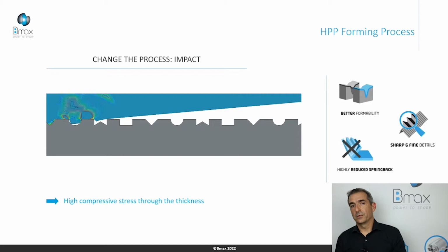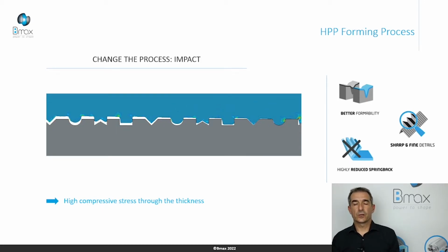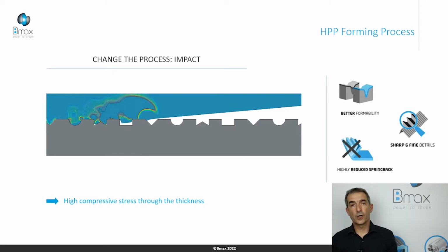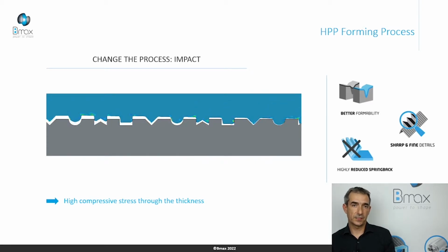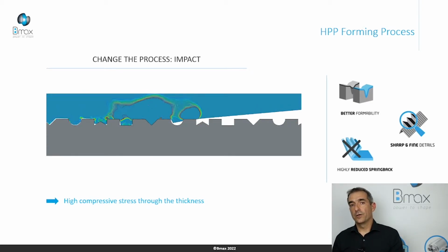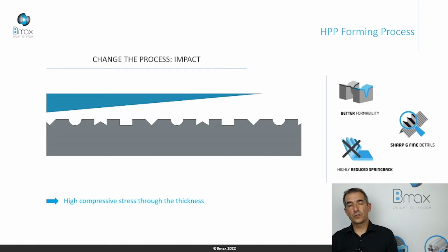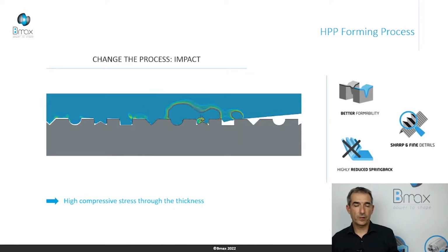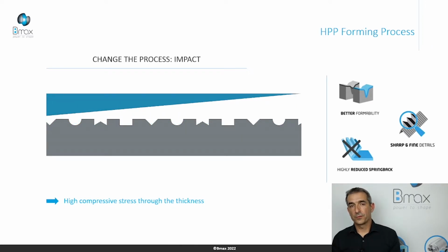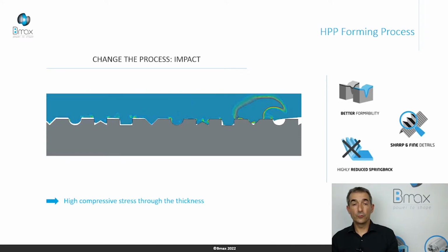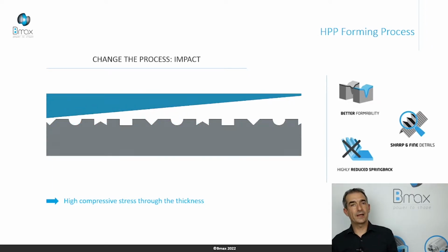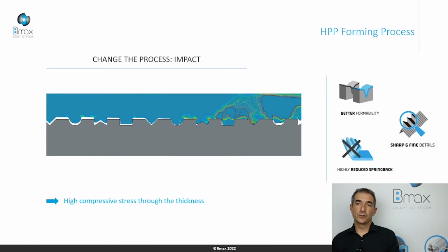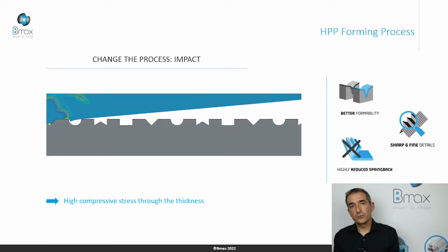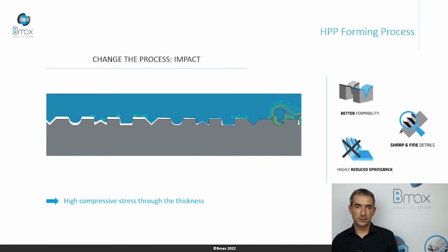The last point regarding the impact is the generation of compressive stress through the thickness. If we consider stamping, forming with a lot of tensile stress along the fiber, a compression along the thickness can remove all the stress. So by the impact, we can change the stress distribution in the blank, and in this way, we can change the nature of the springback.